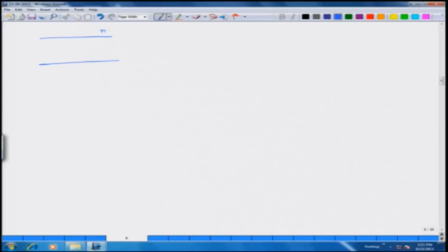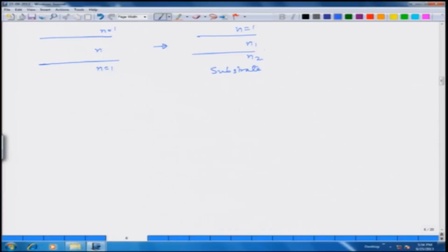I started with a film which had n equal to 1 on both sides, and the film was inside, but in general when I am dealing with devices, probably one side is the ambient, the other side is the film, and here you will have a substrate or some other film which would have N2. So, generally you will have this case. I am not going to rederive it, but instead of writing r prime, you would be writing it between N1 and N2. The formulation will be developed similarly, only the r prime and t primes are going to be different in this particular case.